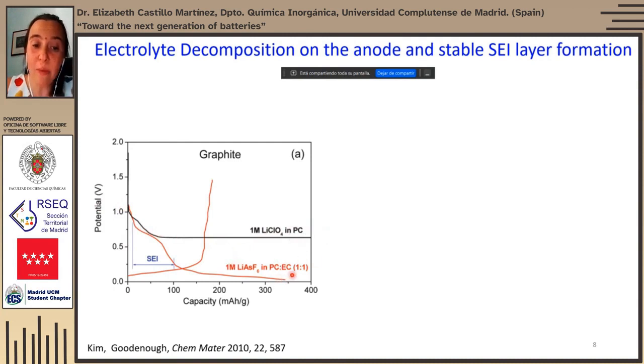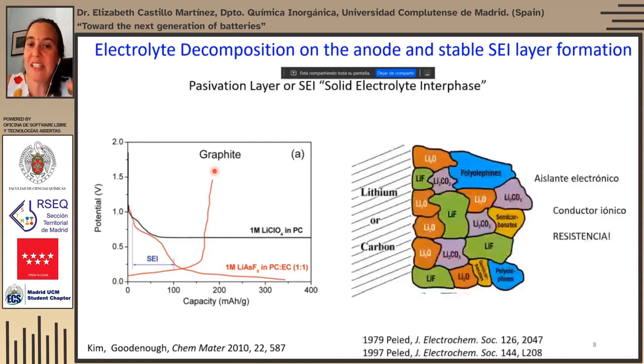The addition of ethylene carbonate to the electrolyte mixture promotes the formation of a passivation layer on top of the material that allows the voltage to continue going down and the lithium ions to insert into graphite, and this becomes reversible. So the formation of this passivation layer has become a very important issue in batteries. It depends a lot on the chemistry of the electrolyte, and it depends a lot on the chemistry of the electrode material.